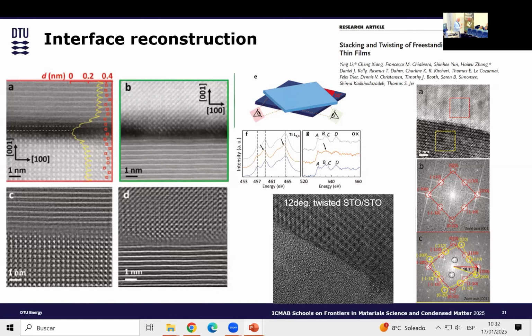How do we do that? We took the surfaces and cleaned them as well as we can, meaning we cleaned them with acetone and then with plasma etching. We put them together on top of each other. We heated them to about 550 degrees in a reduced atmosphere in order to clean the surfaces. And this is what we get. So we got two layers which are rotated relative to each other by 12 degrees.